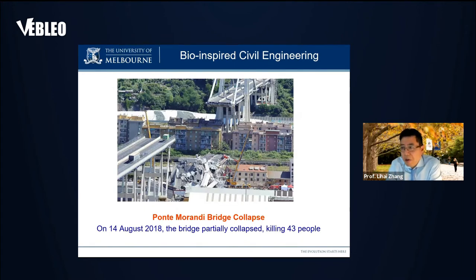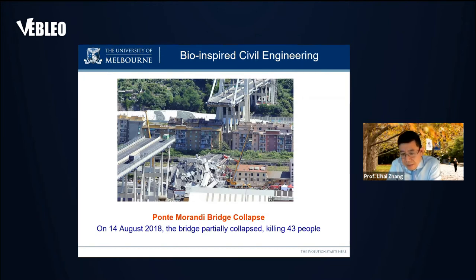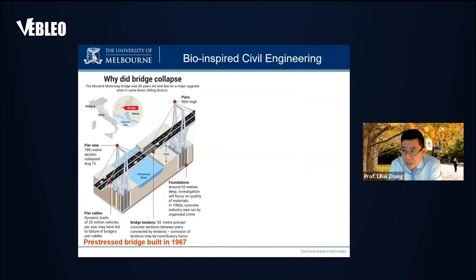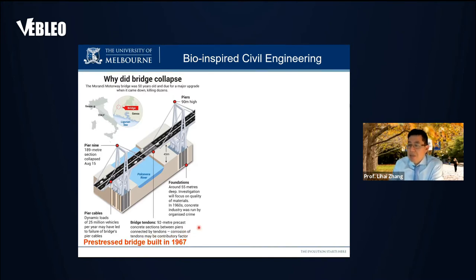Today's talk is about bio-inspired civil engineering — how we learn from nature and apply those lessons to civil engineering. This is the Morandi Bridge in Italy, which unfortunately collapsed on 14th August 2018, killing 43 people. Investigations revealed the collapse was due to corrosion of tendons connecting 92-metre precast concrete sections between pillars, caused by cracking of the concrete.